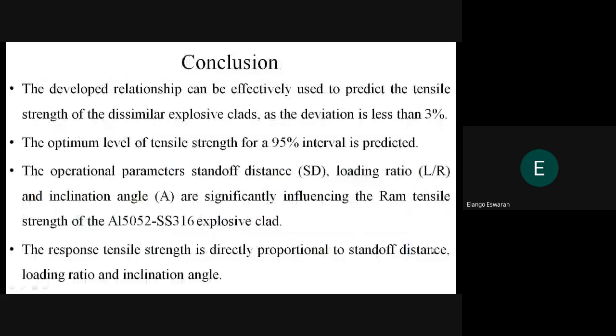Finally, the conclusion: the developed relationship can be effectively used to predict the tensile strength of dissimilar explosive clad. As the deviation is less than 3%, the optimal level of tensile strength for the 95% interval is predicted. The operational parameters, standoff distance, loading ratio and inclination angle, significantly influence the tensile strength of aluminum 5052 SS316 explosive clad. The response tensile strength is directly proportional to the standoff distance, loading ratio, and inclination angle.